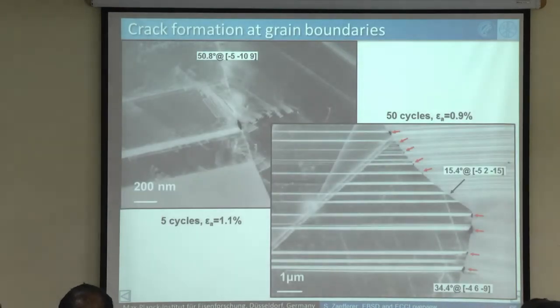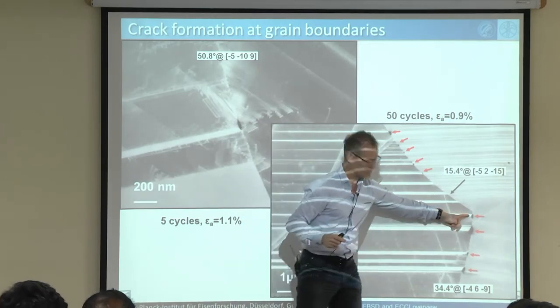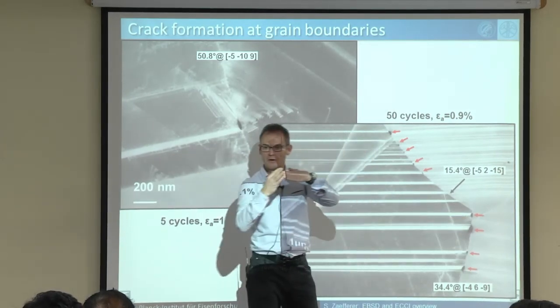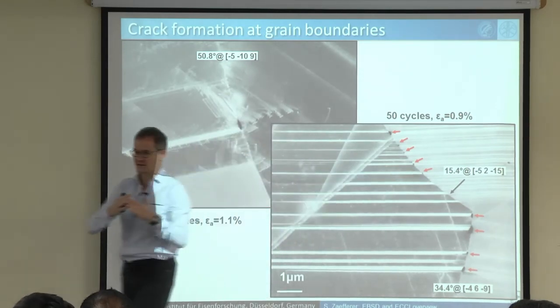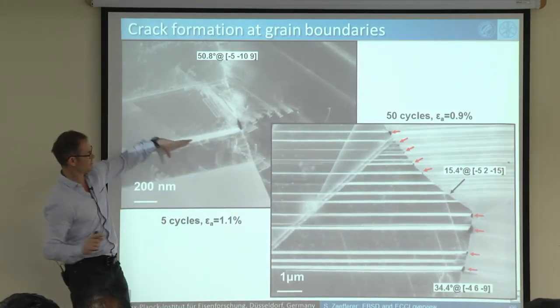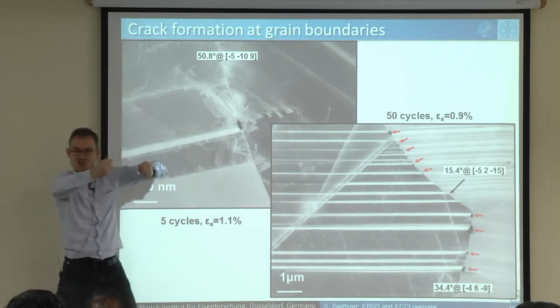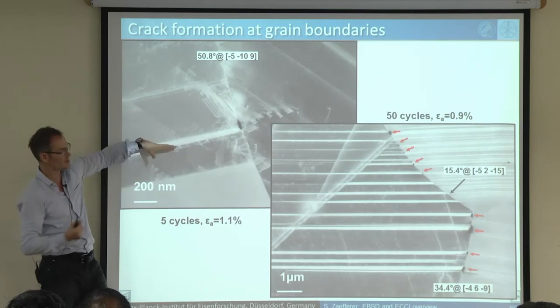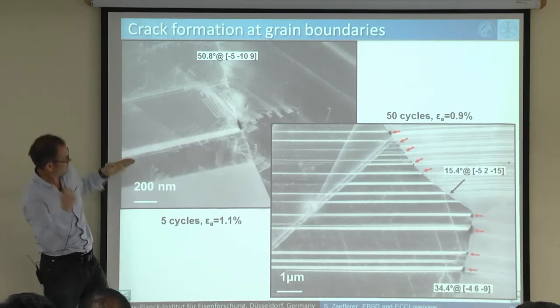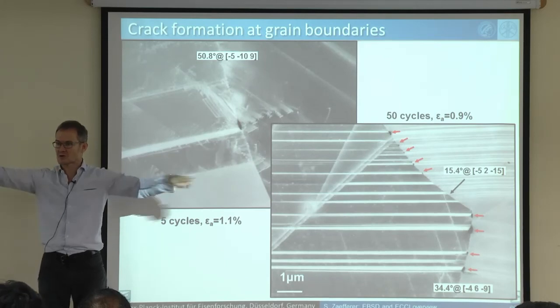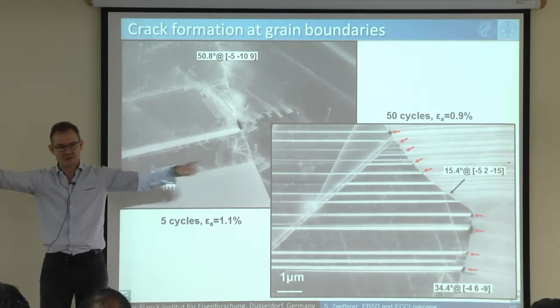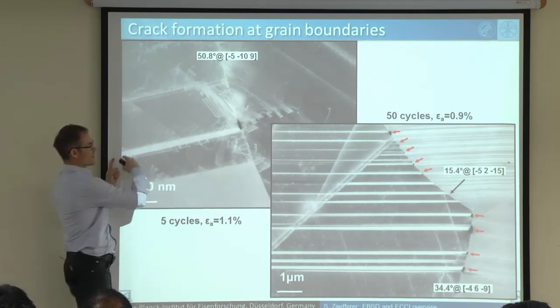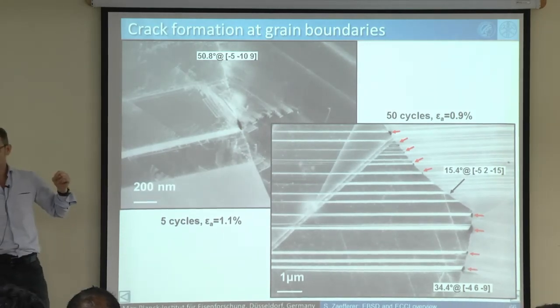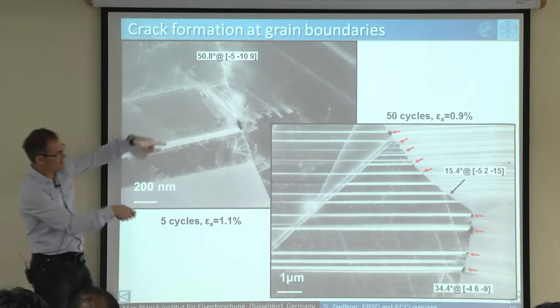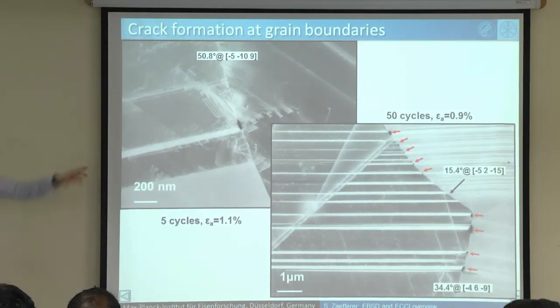Oops, too quick. We could explain why, particularly at these areas where epsilon martensite hits the grain boundary, why we get this very early fracture, this early cracking. And it's actually a number of reasons. One is, when the epsilon martensite arrives here, it shears the lattice locally very strongly, because epsilon martensite is a shear formation. The second is, epsilon martensite forms out of dislocations moving. Yeah? Each partial dislocation makes an epsilon layer, and each partial dislocation transports hydrogen out of the material to this area, to the grain boundary. So it embrittles the grain boundaries additionally to the high strain which we have there. And so this leads very quickly to the formation of these cracks.